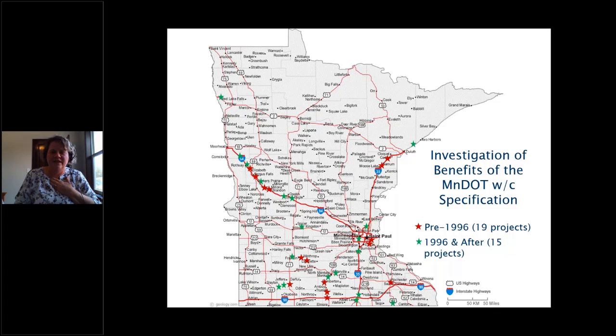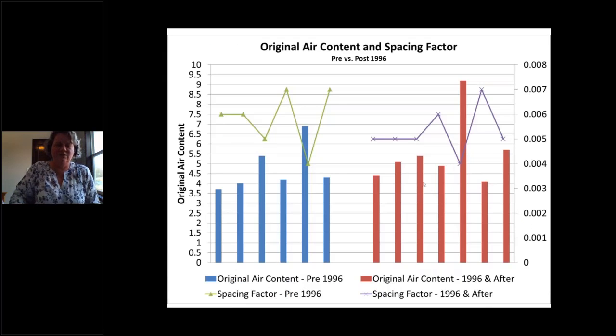So we undertook an investigation on the benefits of the water cement ratio. We looked at 19 projects before the water cement and 15 after the water cement ratio. And these are the kind of things that we found with our cores. We took over 200 cores from these pavements and tested them. We found that our air content, pre and post water cement ratio, was pretty similar. We increased our air content spec in the post era by 1%, but we were generally getting the air that we were expecting in our pavements.